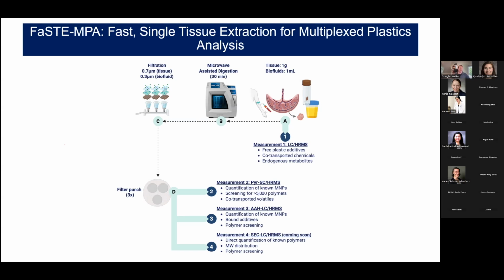their current state. Once we've done that extraction or digestion, and that occurs in a microwave system, it's allowed us to accelerate how quickly we can do that from 48 to 72 hours to 30 minutes. We then take that digest and filter it to allow all of the liquid and dissolved molecules to pass through the filter and trap all the microplastics that are remaining. And the filters we use vary. For tissue, we're using 0.7 micron, or 700 nanometer, filters. For biofluids, the goal is to use 0.3 micron, or 300 nanometer, filters.